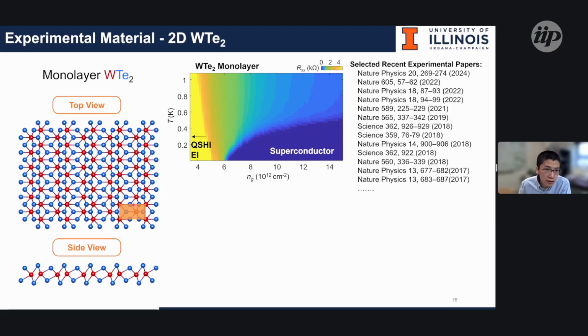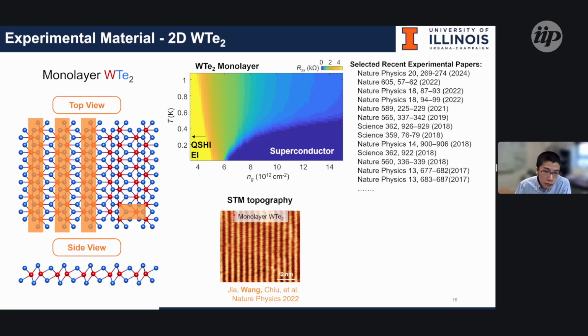You can see that this rectangular lattice has a unit cell structure of around 1 by 2 along the short edge and the long edge. With this, you can see the zigzag chains, which come from the tungsten and form 1D stripes. And with an STM collaboration with Professor Ali Yazdani's group during my postdoc, we were able to observe the quasi-1D channels on the monolayer tungsten ditelluride.